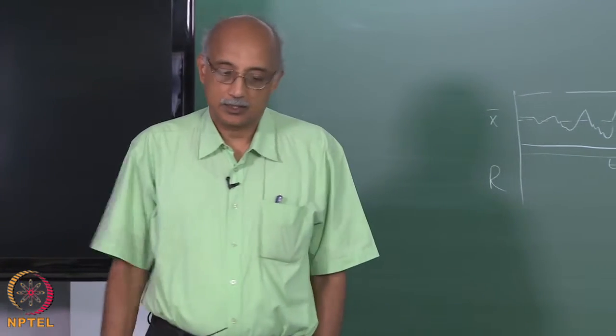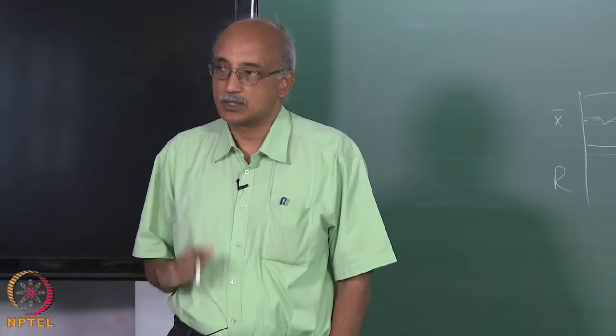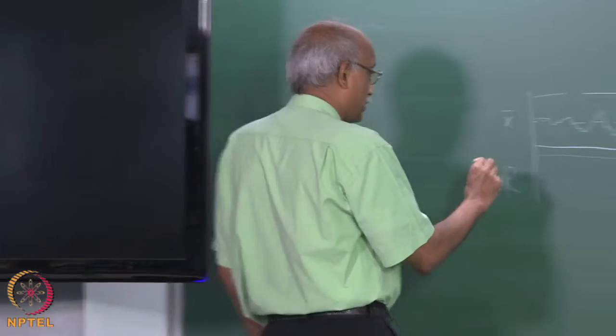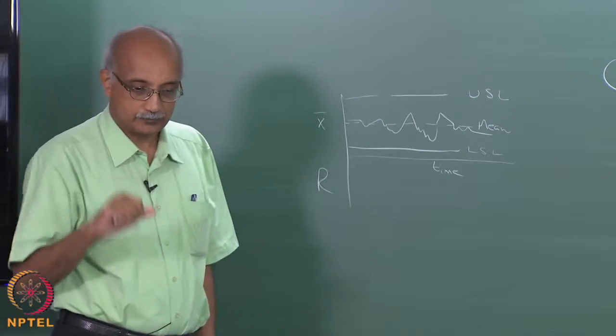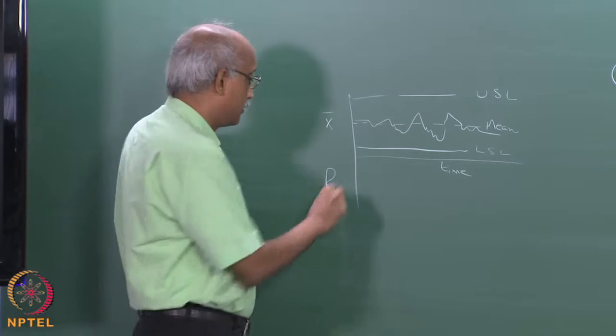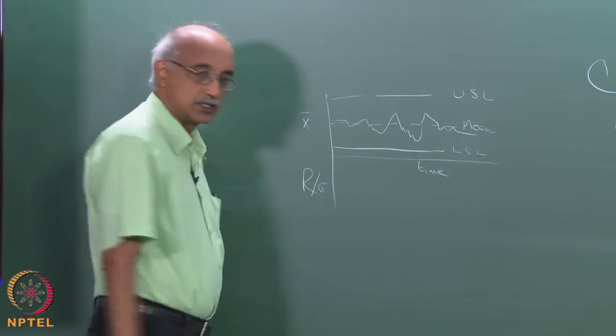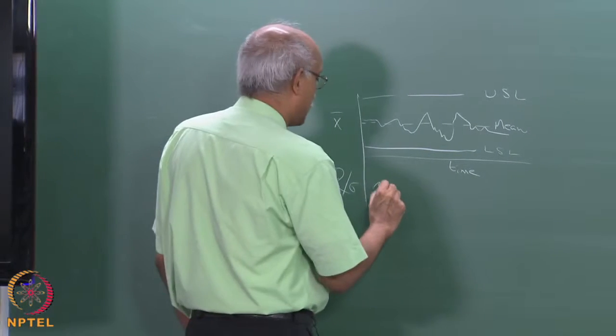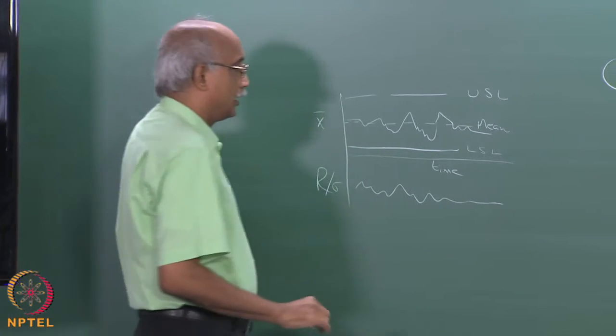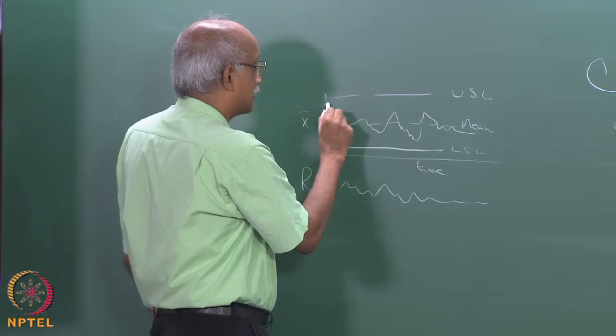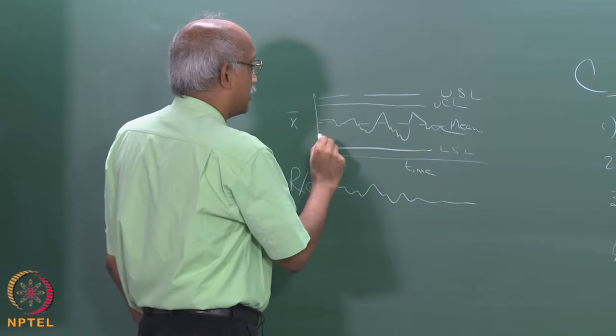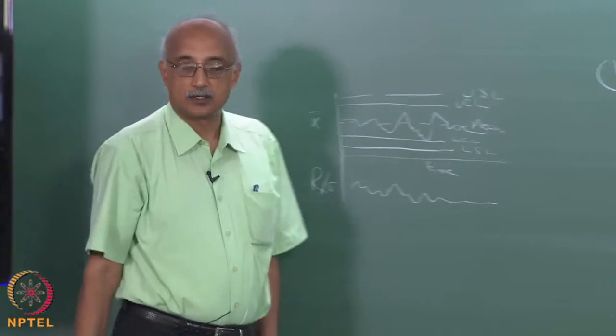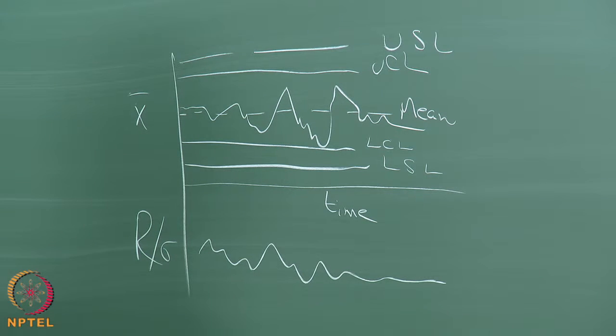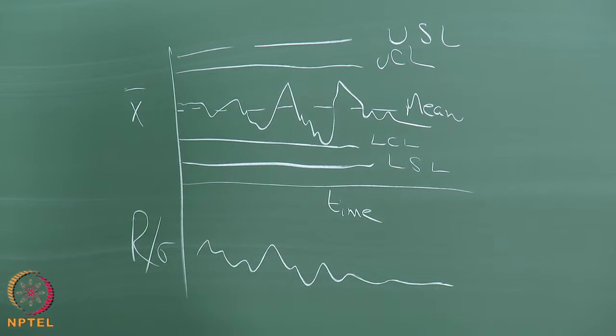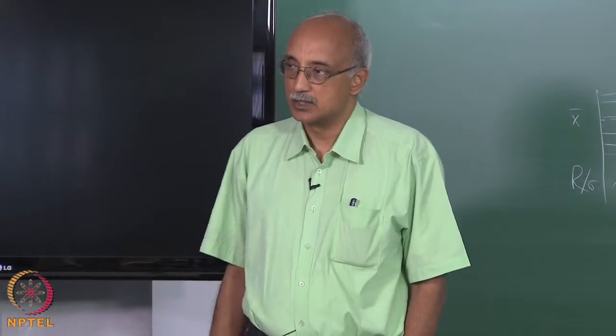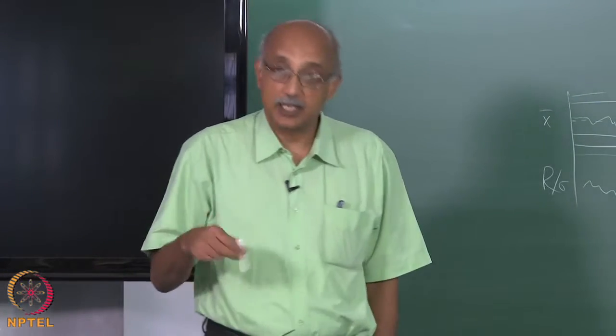But more importantly, in an enlightened Six Sigma factory, they will also be measuring the range. The range is the distance between max and min, or sigma, which is a standard deviation, and that would also be monitored as a function of time. And in addition to the spec limits, control limits will be established, UCL and LCL. The difference between a control limit and a spec limit is that the specification limit is imposed typically by the customer or the product requirements. The control limit is derived from the behavior of the process.